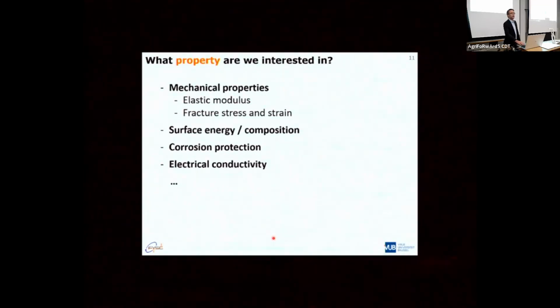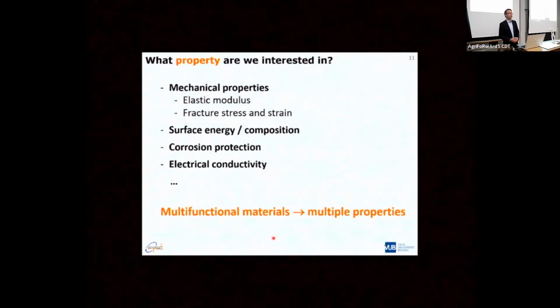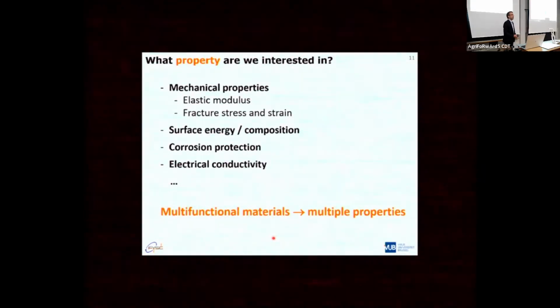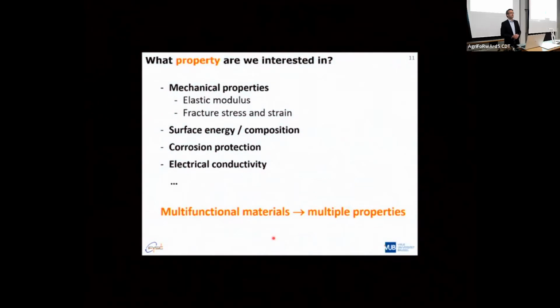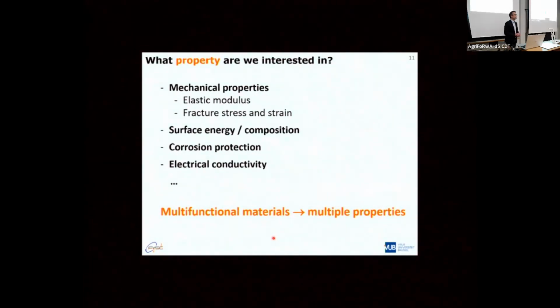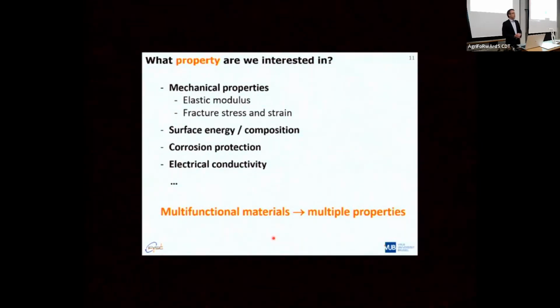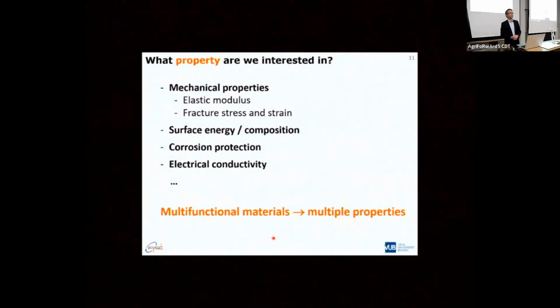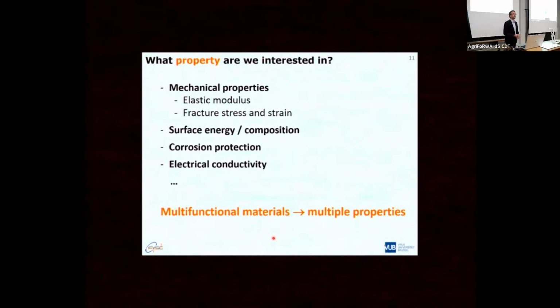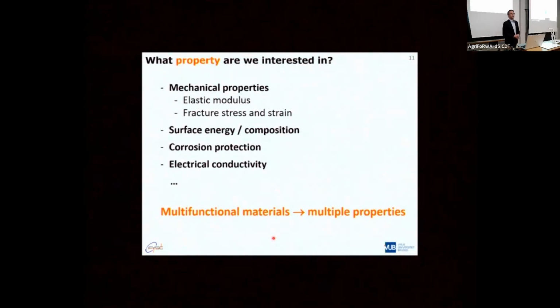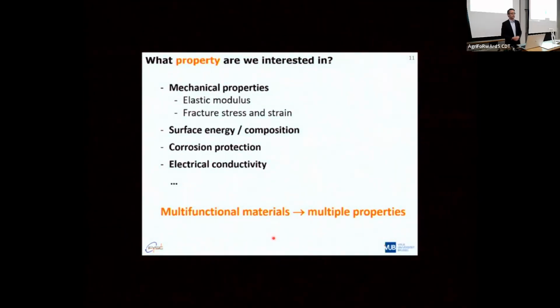I, at some point, worked on printing plates, lithographic printing plates that you irradiate with a laser. And the first thing the company told us, yeah, these are the irradiation conditions, and you should be able to get sufficient contrast between hydrophilic and hydrophobic regions to be able to print. About 4 years later, at the end of the project, there was a list of 13 other properties that were important for printing plates. It's never about one property that your material should meet. It's always about a combination of properties, even if you stay with very simple systems.